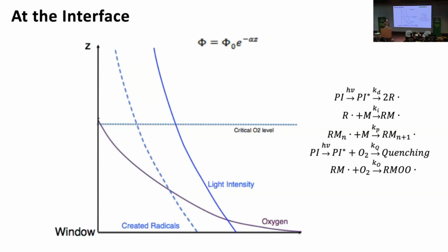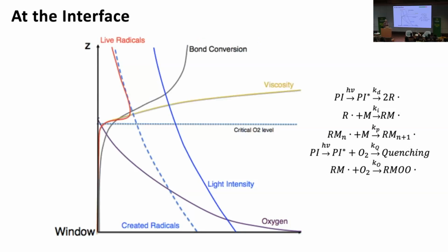Now, in polymerizations, once you form a radical pair in an organically polymerizable medium that has oxygen, that radical will do one of two things. If oxygen is present, the rate constant for reacting with oxygen is much higher than the rate constant for initiating a polymerization. So if there's oxygen present, the radical will be consumed by the oxygen. And so the oxygen is depleting as a function of distance up into the resin because the oxygen is being replenished by the window. As the oxygen gets depleted, it's a semi-permeable membrane that will allow oxygen to go back and replace it. So there's a gradient of oxygen concentration by the window where the light's illuminating. And once the oxygen concentration gets down to a certain level, then the polymerization will take place. And this will have the polymer forming, and this distance is the dead zone thickness.